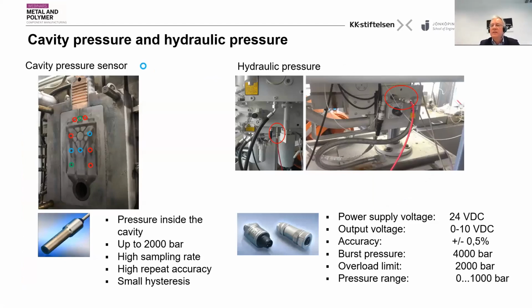The first thing on the left-hand side here you see is cavity pressure sensors. And I think that's very important because you only calculate pressures from the third stage, plunger pressure, into the melt. But now you can see with these cavity pressure sensors, which hold up to 2000 bar, and they last a very long time. We never made 100,000 shots with them in the lab, but I think they last at least 10,000 shots or something like this. So they're ready for industrial application. You get information about cavity pressures inside the die, and this really is important for the quality of the part. On the right-hand side, of course, you have classical hydraulic pressures, which are used for a conventional shot chamber, shot profile already today.